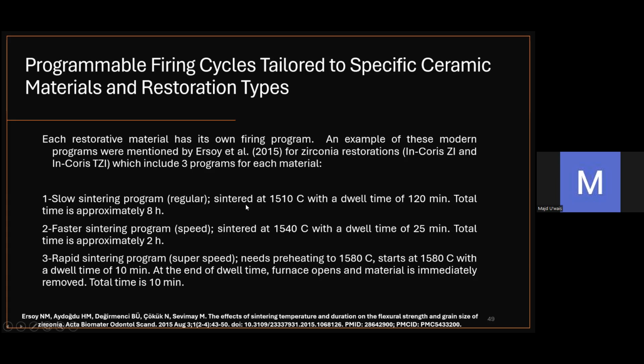So for this brand, for example, there were 3 programs. The first program is the slow sintering program, which is the regular one. Sintering was done at 1510 Celsius, and the total needed time was 8 hours. The second program, which is the faster sintering program, used a higher temperature than the previous one, and the total time was 2 hours. And the third one, which is the super speed program, used an even higher temperature than the previous 2, and the total time was only 10 minutes.